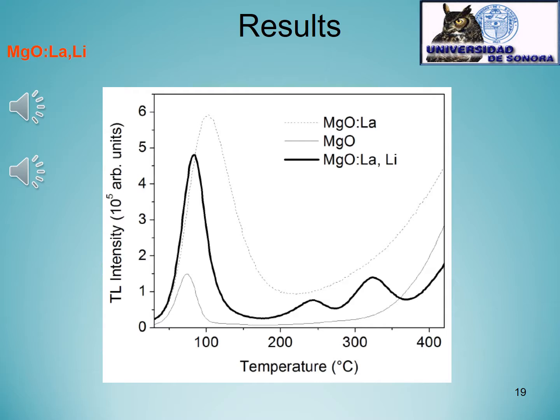In this case, analogous to the cerium lithium doped sample, we could observe the compensation charge effect of lithium on the lanthanide sites in the crystal structure of magnesium oxide.